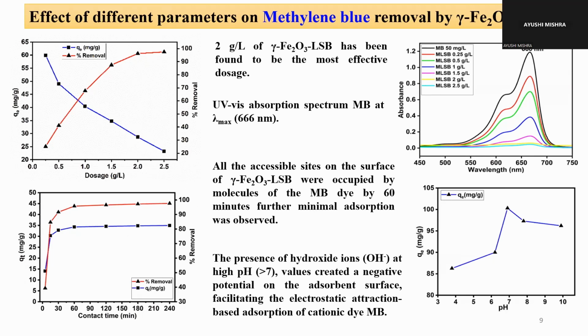We have also checked the effect of pH on the adsorption process. In acidic pH, when we have more H+ ions, there is competition with methylene blue, which is also a cationic dye. H+ is also cationic, and H+ moves faster and captures all the active sites, so methylene blue adsorption was not much at lower pH. At higher pH, when the hydroxide ions are greater in number, we have a negative potential on the adsorbent surface that facilitates electrostatic attraction between the cationic dye and the adsorbent surface, the magnetic biochar.